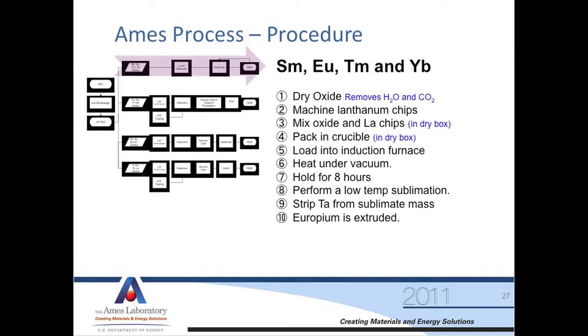Then we'll do another step where we sublime it. And then we simply strip the tantalum off, like you're opening a sardine can. For europium, the next step is that we extrude the europium into rods. The reason we do that is to reduce the surface area of the material because it's so reactive with air.